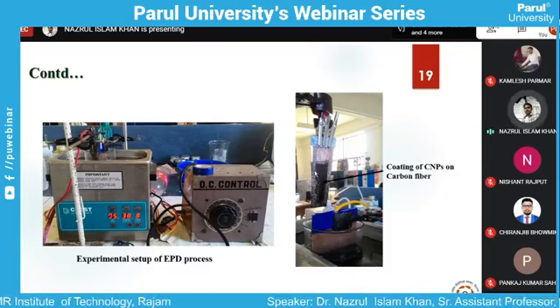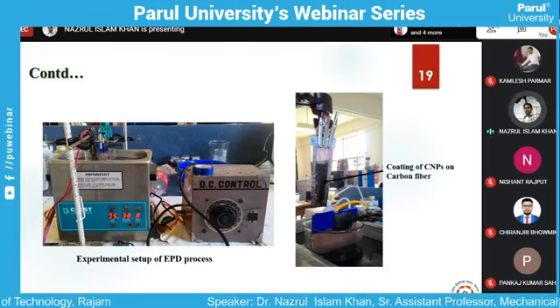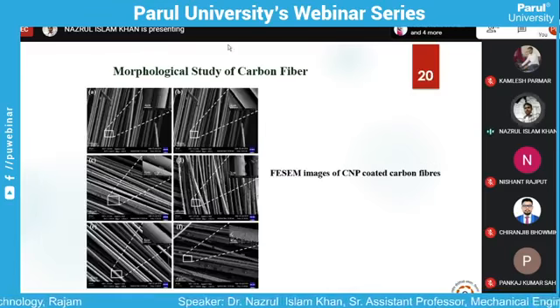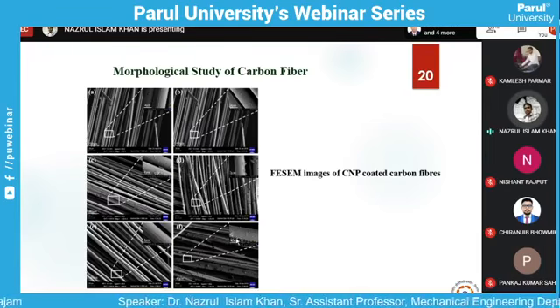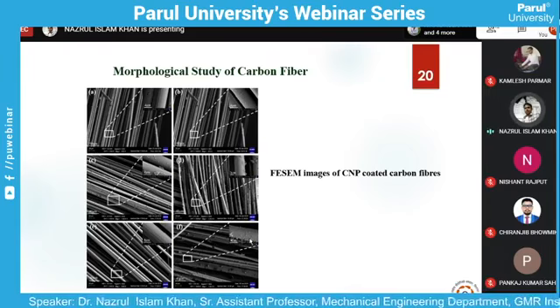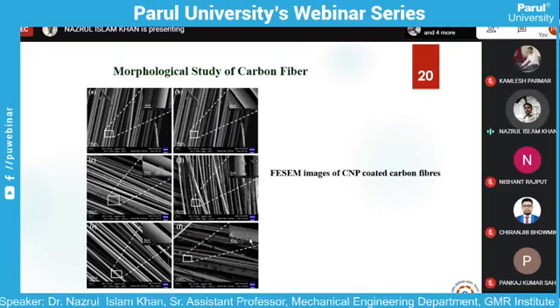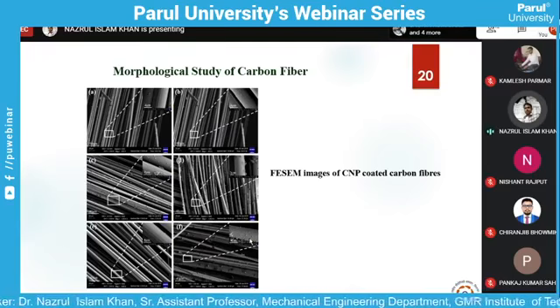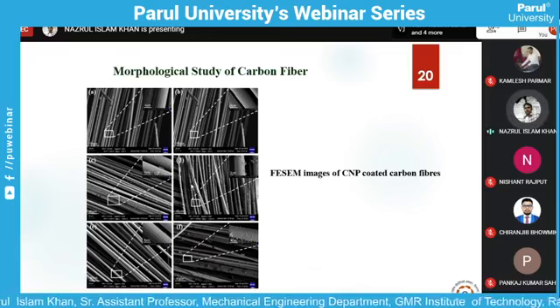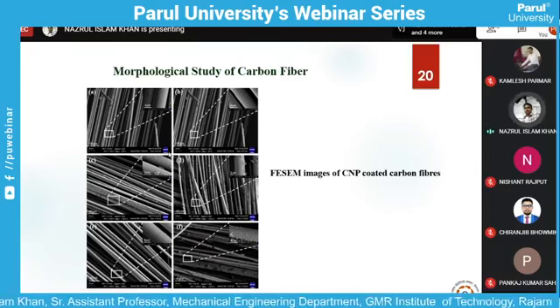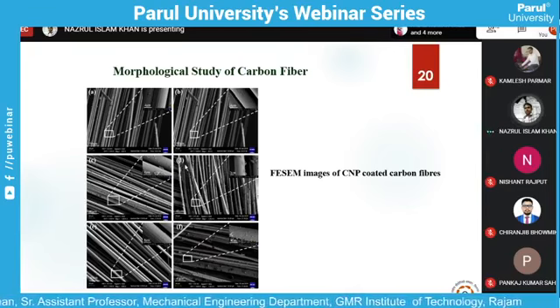So if you change the surface properties of carbon fiber, then also you can change the mechanical properties of CFRP composite. From this surface characterization of carbon fiber also we can have that. We can see in the last picture the roughness, and in the first picture there is a significant change in surface morphology, mainly due to the attachment of those carbon-based nanoparticles on the surface of the carbon fiber.